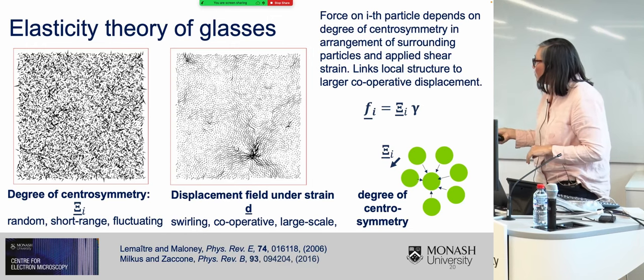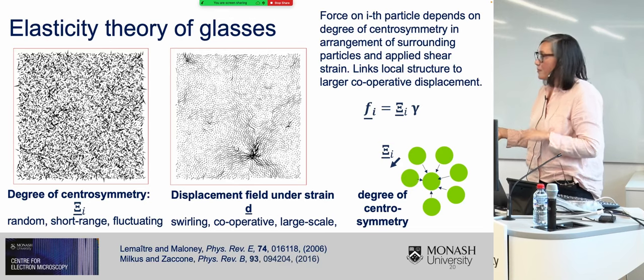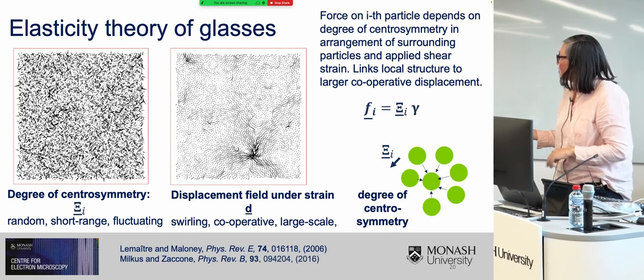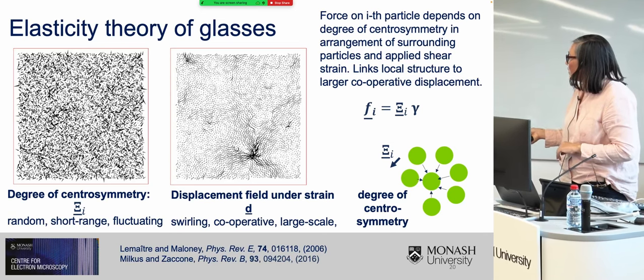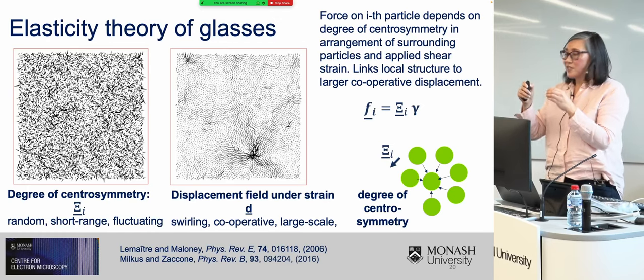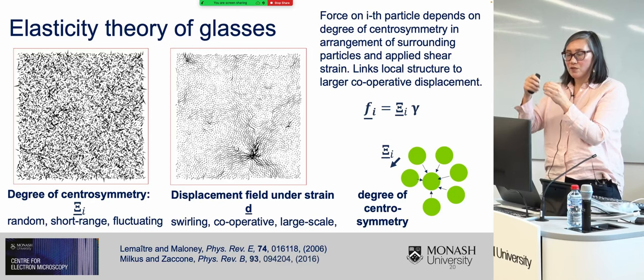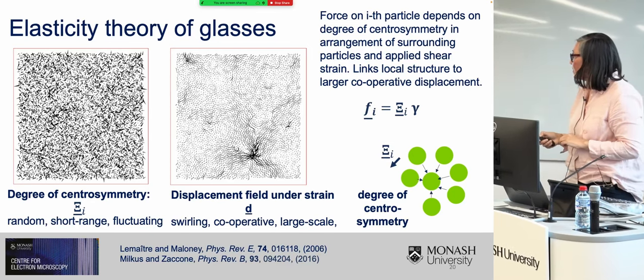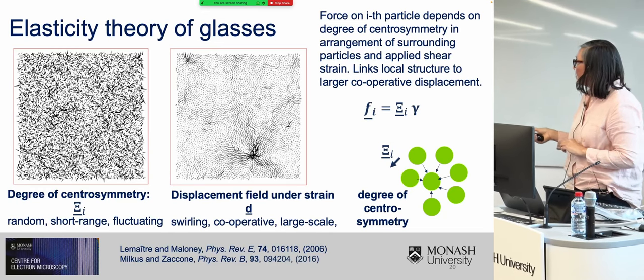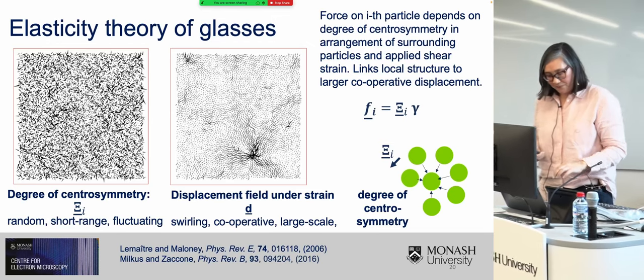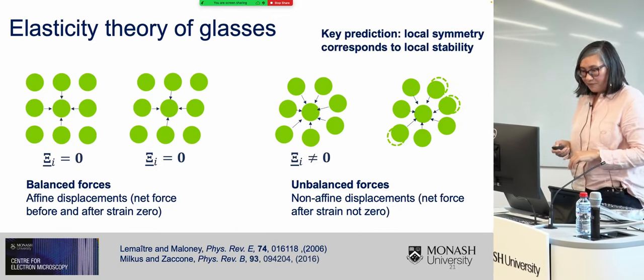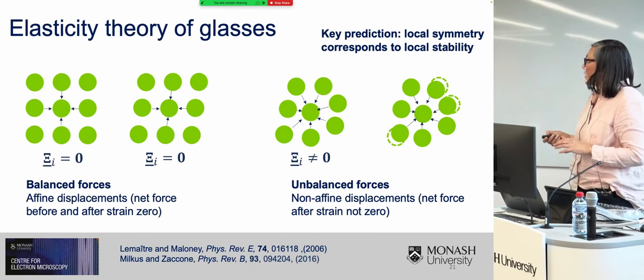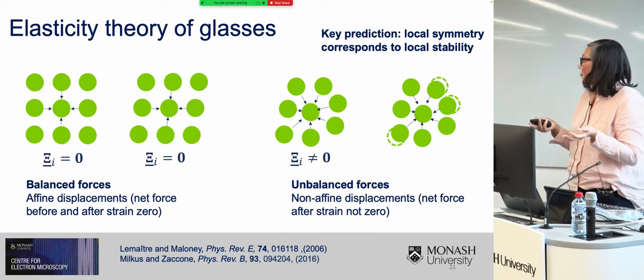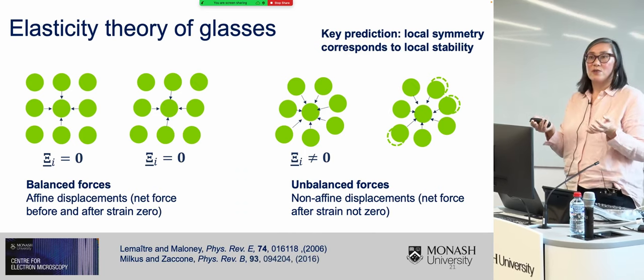So for example, if you plot out this degree of centrosymmetry, and here I've taken these plots from this publication, you can see it's random, it's very short range, and it fluctuates. But then if you plot out the displacement field after strain, so the displacement direction and magnitude of individual particles from their initial configuration to their final configuration, you can see these large swirling cooperative and large scale motions. And somehow these motions are linked to the local centrosymmetry, and also the propensity for the non-affine displacements.